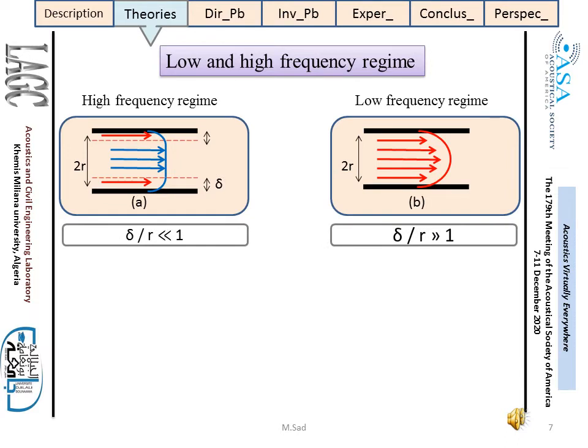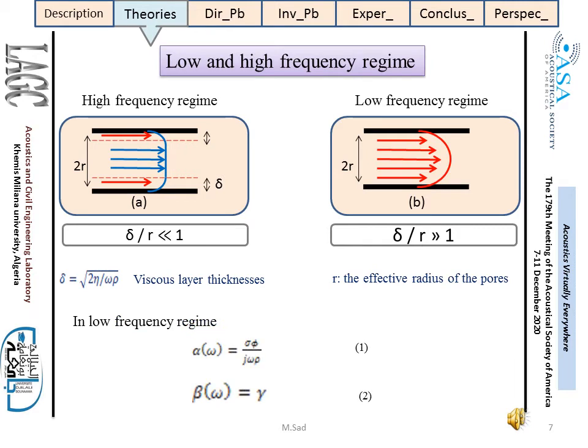To differentiate between high and low frequency regime, the viscous and thermal skin thickness are compared at a given frequency with the effective radius of the pore. The low frequency range is defined when the viscous and thermal skin thickness are greater relative to the pore radius. Otherwise, it is the high frequency range. In the Darcy regime, flow without any inertial effects, corresponding to the very low frequencies, the air flow resistivity is the most important parameter describing the viscous losses caused by fluid structure exchanges. In this case, the dynamic tortuosity alpha of omega and the dynamic compressibility beta of omega are given by equations 1 and 2. In these equations, j is the imaginary unit, phi is the porosity, sigma is the flow resistivity, rho is the saturating fluid density, and gamma is the adiabatic constant.